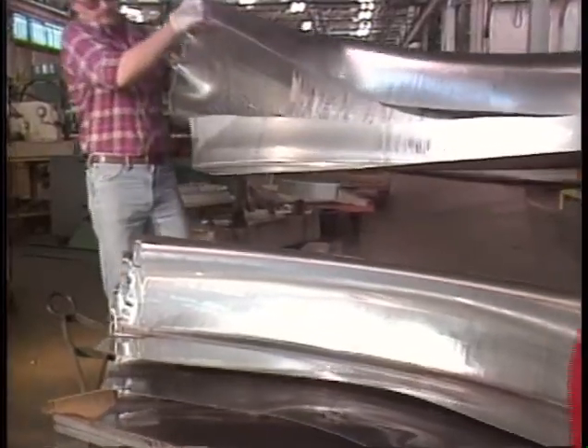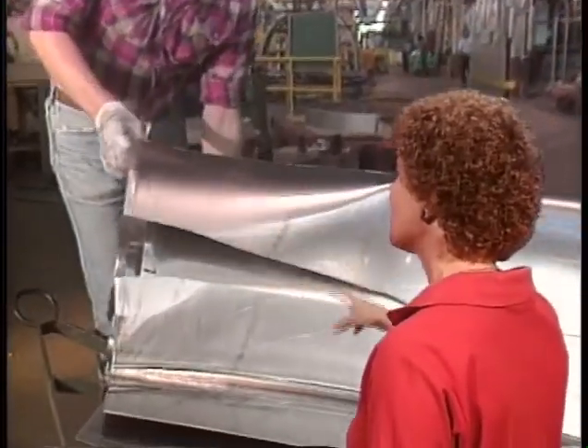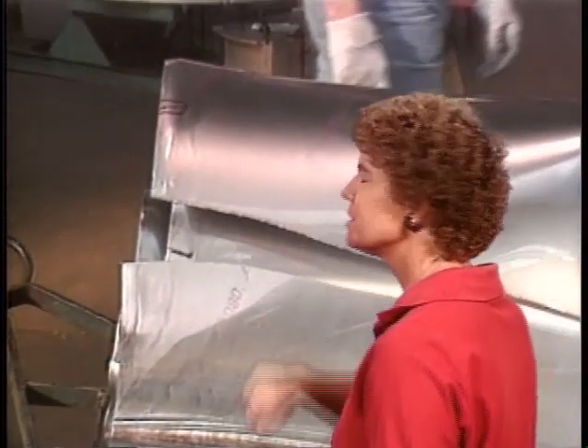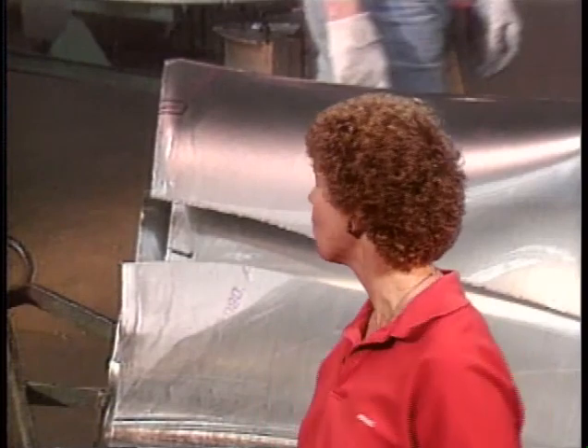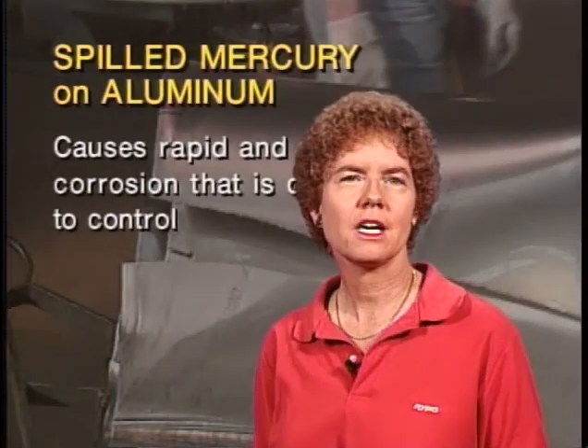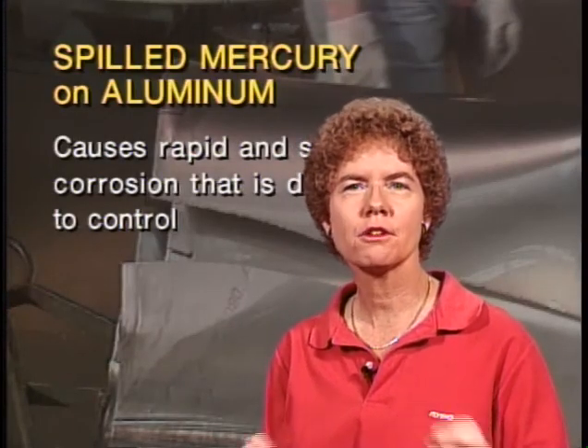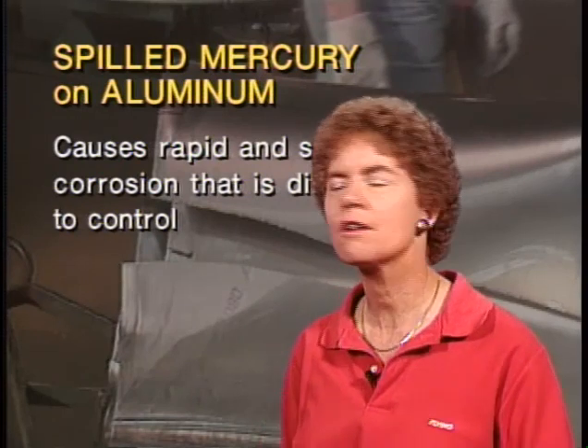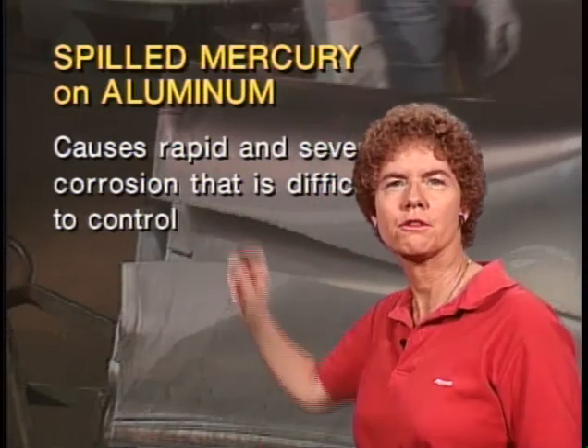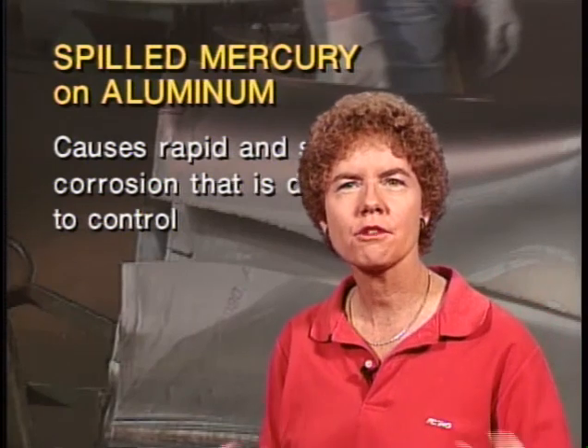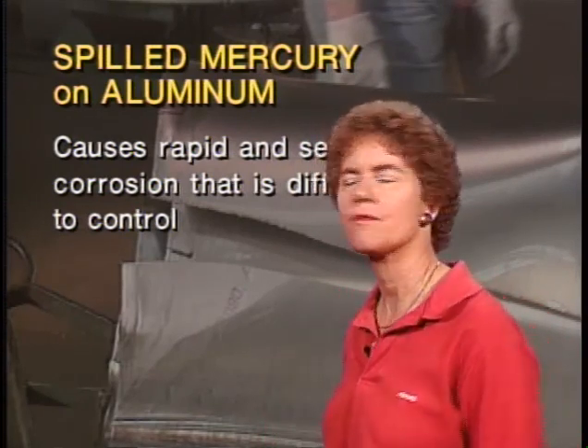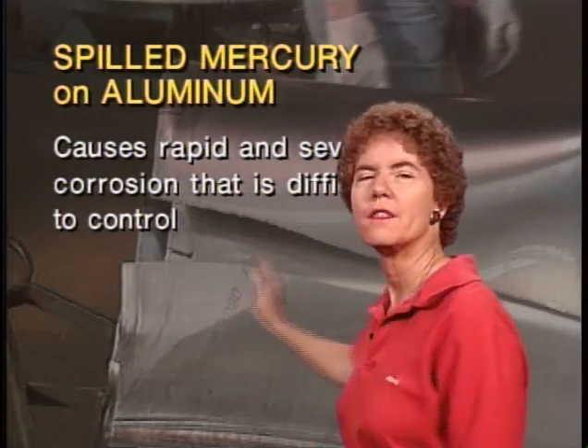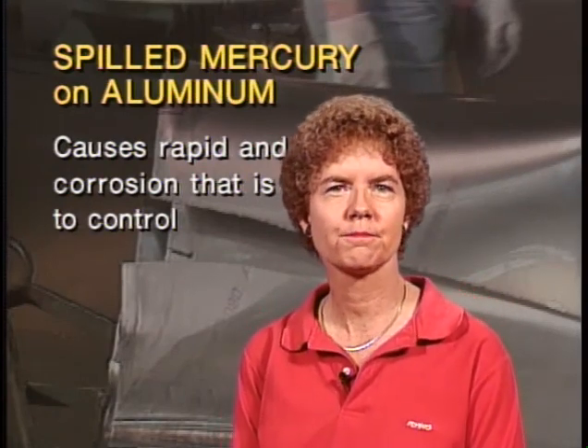So you don't want caustic cleaning products to be in contact with aluminum because you don't want them causing the corrosion. Now this is some shiny, bright new aluminum, but let's assume that you accidentally spilled mercury on that aluminum. What's going to happen to you? What you're going to get is rapid and severe corrosion of the aluminum that is very difficult to control. The mercury is going to cause pitting and intergranular attack, a lot of rapid and severe corrosion that is very difficult to control.